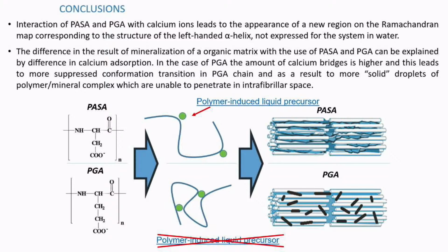Polyaspartic acid, it is known, can form a polymer-induced liquid precursor. It's like a liquid-like droplet that can easily be involved in the organic matrix by osmotic pressure and induce mineralization in it. But if we don't use any polyelectrolyte, the mineral phase is more solid and cannot go into the organic matrix, and only the surface is mineralized in this case. In the case of glutamic acid, the situation is very similar, because the collapsed chain of glutamic acid cannot form such a liquid-like precursor, and droplets are more solid and again cannot penetrate the organic matrix.